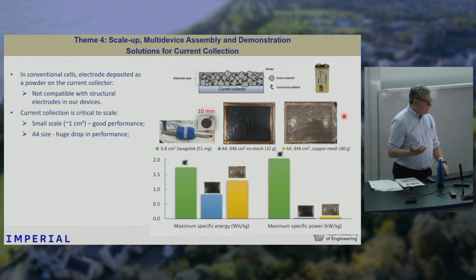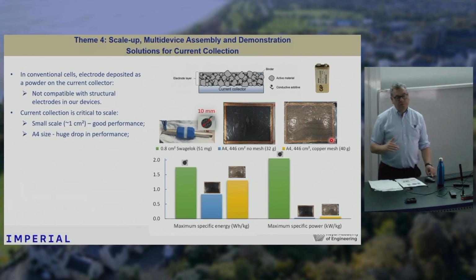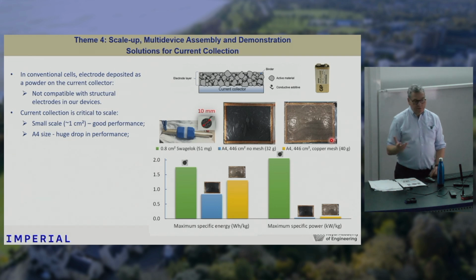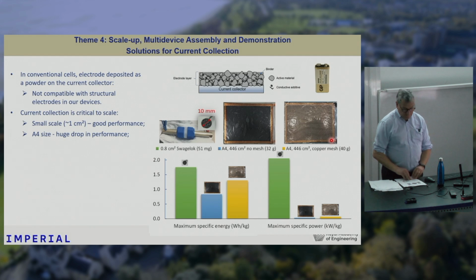And we found that there was a huge drop-off in performance. The capacitance, so that's related to the specific energy, dropped by about half, and we could recover some of that by going to this copper grid, but that copper grid was heavy. But the power was really the big problem here, because the Swagelok cell was giving us, say, about 2 kilowatts per kilogram. If we went to this size, we had this enormous drop-off in performance. And the reason for this is electrical losses in the system.